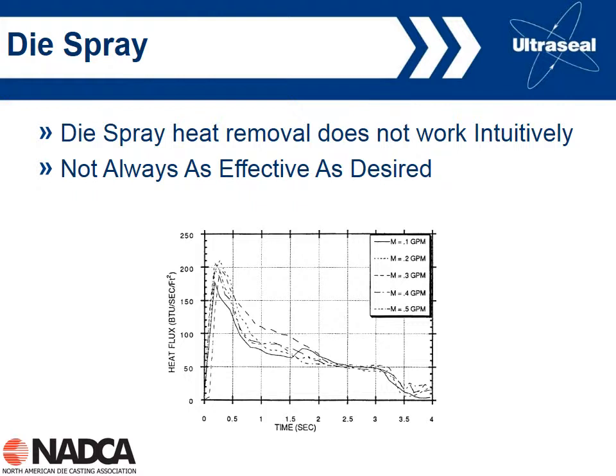In fact, we might actually be hurting ourselves, because if we have a higher flow rate, we're getting more lube on the die, as we talked about last week. That can cause more porosity. We've got more water around, and if we don't get rid of all the water, we may get vaporization and porosity in that way. So it's reasonably limited in terms of what we can do with spray. We don't have total control over the die with spray.